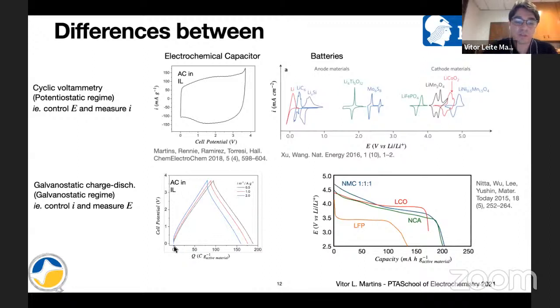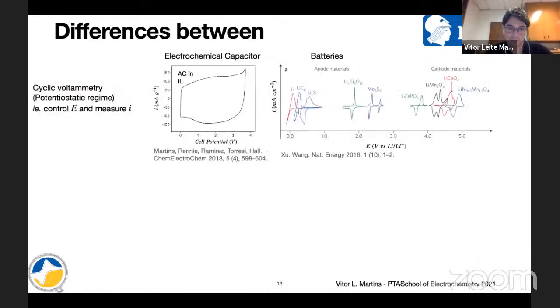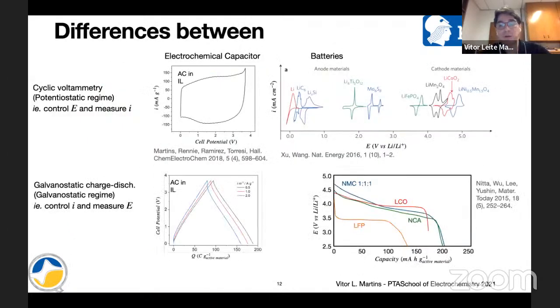So when we are measuring this kind of experiment, you are seeing the voltage variation with respect to time. But when we are plotting to compare with other things, you can multiply the time from the measurement with the current that we applied, right? And then we have a linear dependence of cell potential with time or charge being stored in the device. This is for a capacitor. But for a battery material, you have a different kind of profile. So we have discharge profiles here for those different materials. And see, you have plateaus here. So LFP, you can see very well the 3.5 volt plateau of LFP.